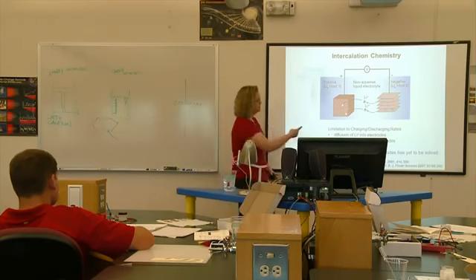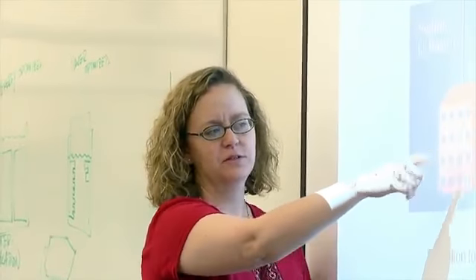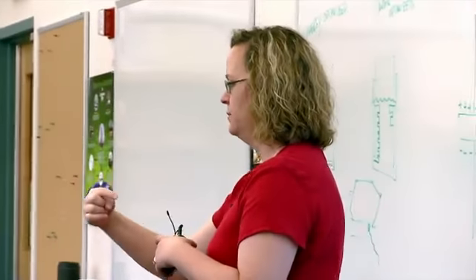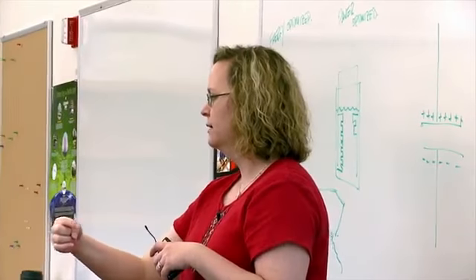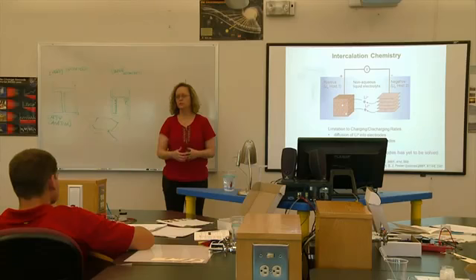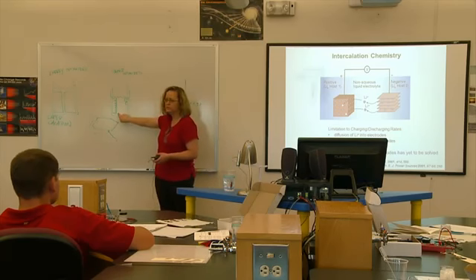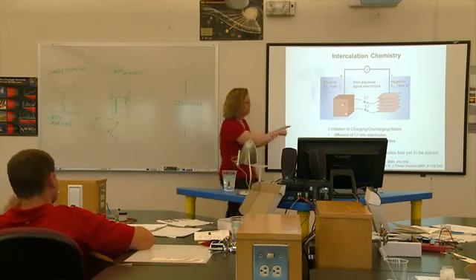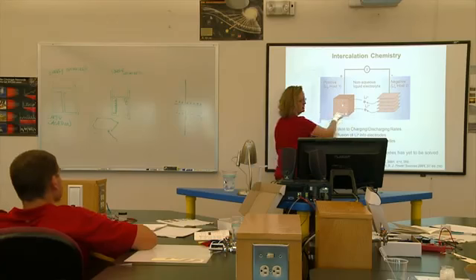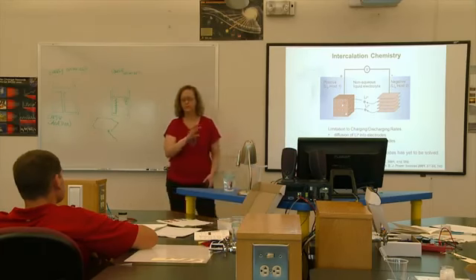And then the other problem is once the lithium ions get to the surface of this electrode, more lithium can't come in until the first guys get to the middle. And we call that solid state diffusion. It's really slow, especially at room temperature, it's really slow. People have figured out if you take those electrodes and make them very high surface area, this volume expansion isn't as bad, and the lithium ions don't have as far to go. So that piece of it will make the battery charge faster, and that's what this does. You're just making more surface area, less bulk. But the problem is you still have this diffusion from this side to this side. So that problem nobody's solved yet.